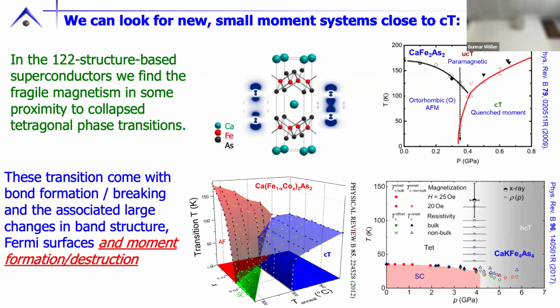And what I want to go over then is a way of trying to find this in systems that show collapsed tetragonal phases. Now, this is the ThCr2Si2 structure. This is CaFe2As2. And what I want to show you is, here's calcium, here's arsenic. Remarkably, I'm going to be ignoring the iron here. At ambient pressure, I do not have bonding across this calcium layer, but with very modest pressures, oh, I get bonding. I go from an 11 angstrom to a 10 angstrom unit cell, and I also lose all magnetism.